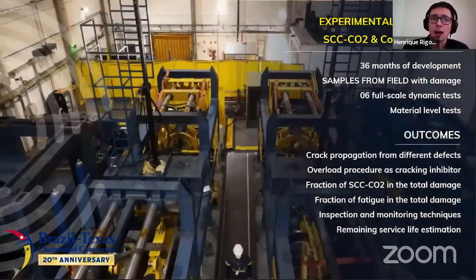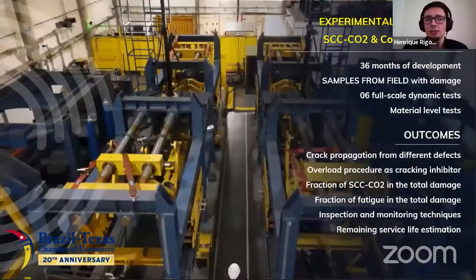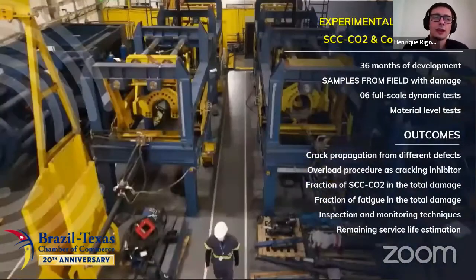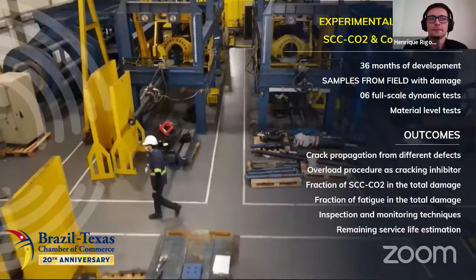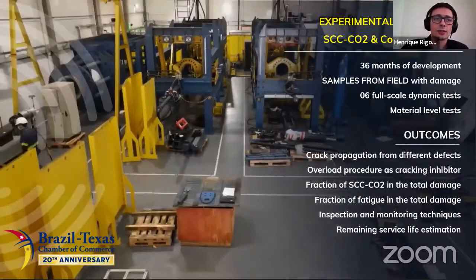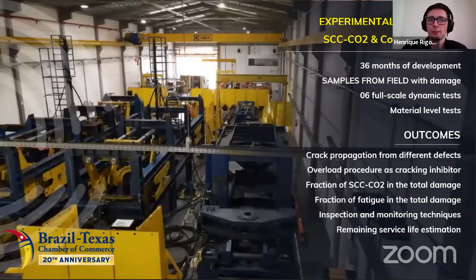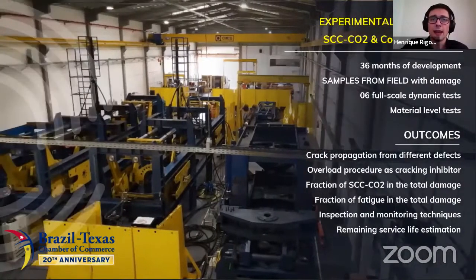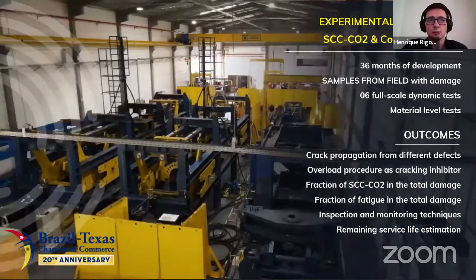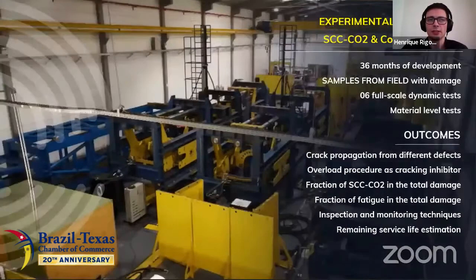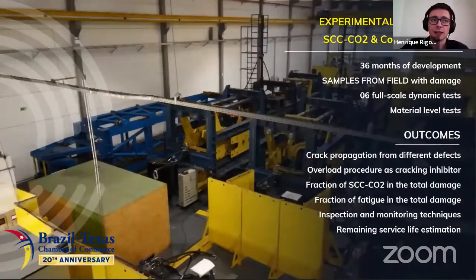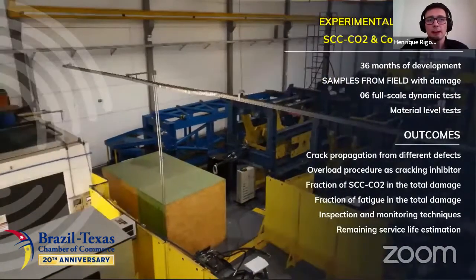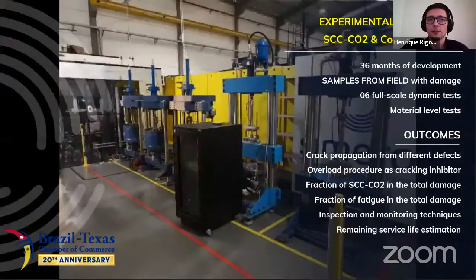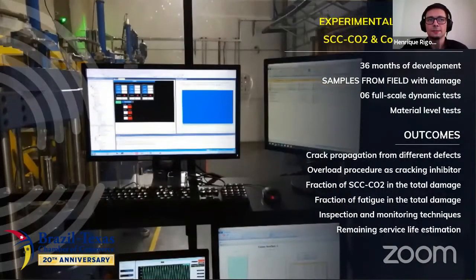These pipes have a high probability to have damage initiation in the structural layers due to the SCC CO2 phenomenon. A dissection process takes place after receiving the samples in order to evaluate the actual degradation state of the structural armors and to confirm the predicted damage. The dissection then delivers a complete defect mapping that is the basis for the following steps of the project.